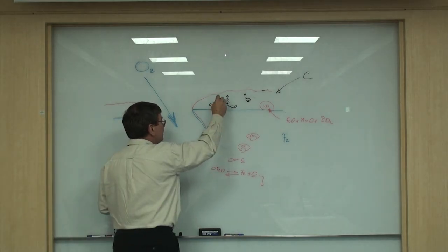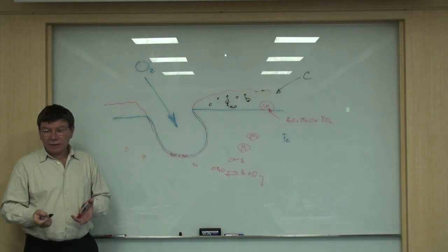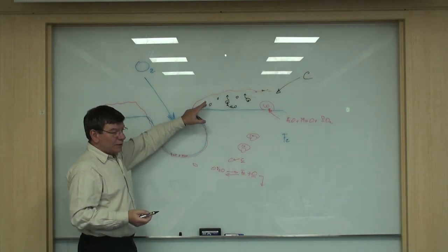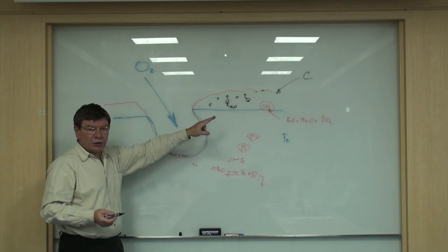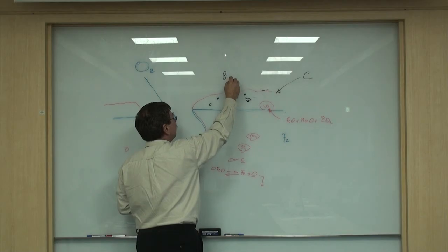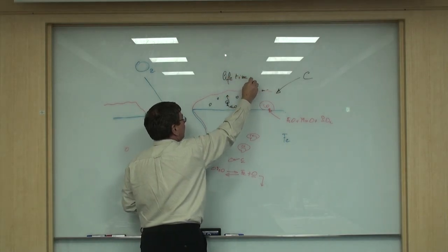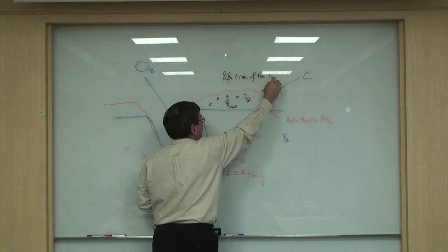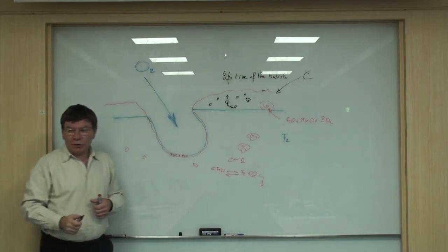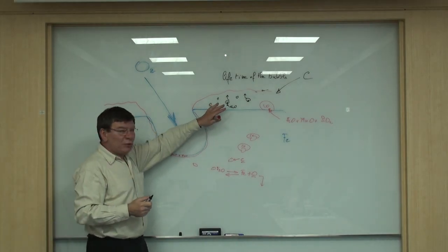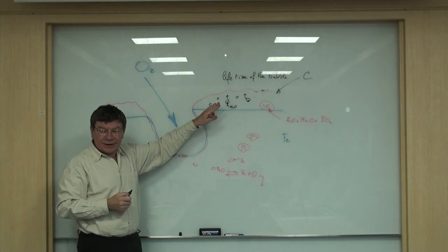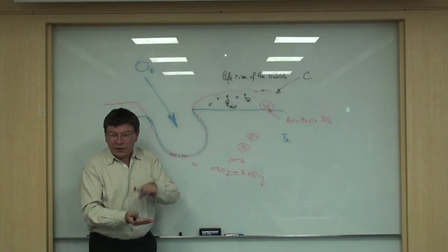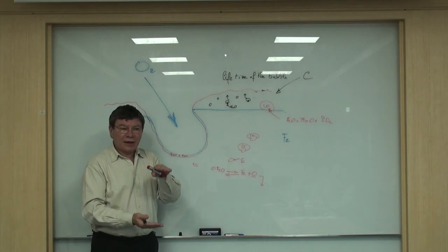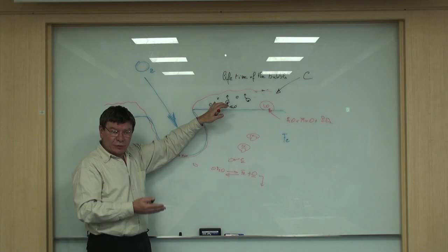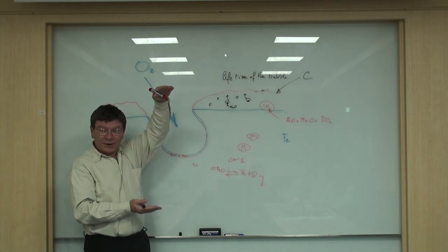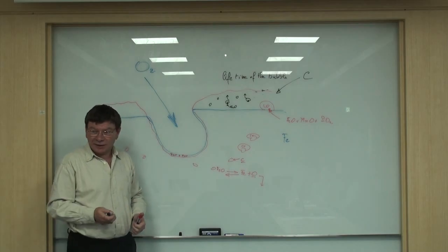And the amount of bubbles and the viscosity of the slag and the conditions at the interface between the slag and the bubble create the lifetime of the bubble. The lifetime of the bubble is the time where the bubble exists in the slag. If you have a small lifetime, you have low foaming slag. If you have a high lifetime, you keep a lot of bubbles in the slag for a long time, so you have high foam. Okay? Easy to understand, yeah? This is like the beer.